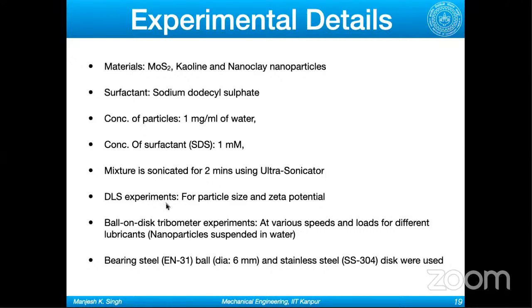Then we did the DLS experiment to get the particle size and zeta potential. Thereafter, we did ball on disk tribometer experiments at various speeds and loads for the different lubricants, that is, nanoparticles suspended in water. The material used in the experiment was bearing steel, EN31, of 6 mm diameter, as the ball in the ball on disk tribometer experiments. And the disc was stainless steel, SS304, which was used as the substrate for the experiment.